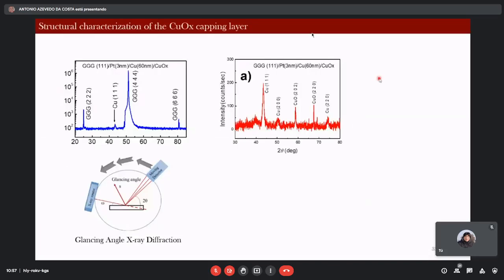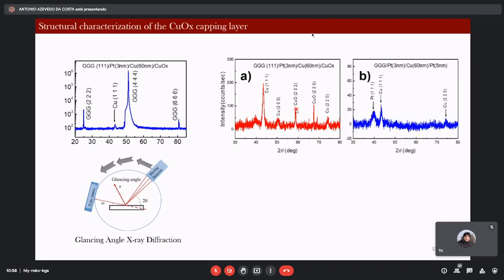So we made the structural characterization by using glancing angle X-ray diffraction. In this case, we deposited a thick layer of copper and left it to oxidize. The copper is thick because we would like to use X-ray to detect the oxidation process. And we can see here there are copper oxide peaks coming from the oxidation. So we can really get a copper oxide layer just by leaving it at ambient conditions, in air. In this case here, we deposited a platinum layer on top of the copper just to protect it, so we didn't detect peaks coming from the oxidation process.